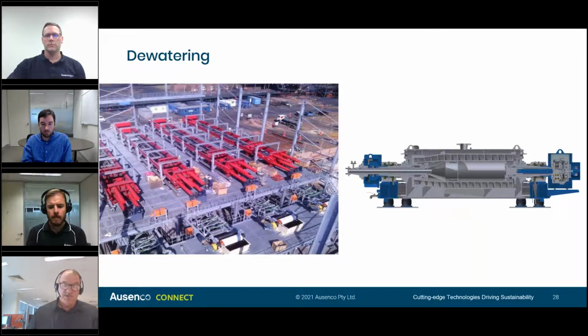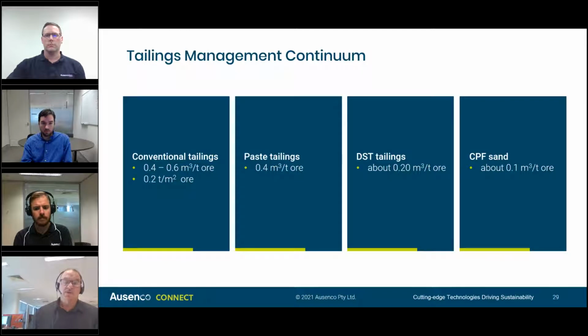So in coal, we've helped out a number of clients in disposing of waste, be that dry waste or in co-disposal. We've helped, for example, people with pumping problems and moving both coarse and fines out to the tailings dam. So the other option is obviously you could look at other options of dewatering, dropping this onto a conveyor belt, conveying it out, or putting it in a truck and trucking it out. The important point, though, is that placed tailings will be compact, and therefore will have a lower void ratio and a higher shear strength compared to hydraulic placed tailings.